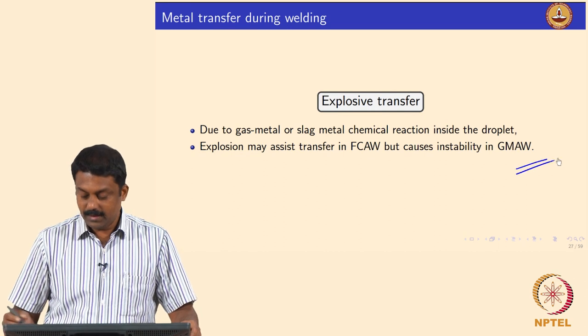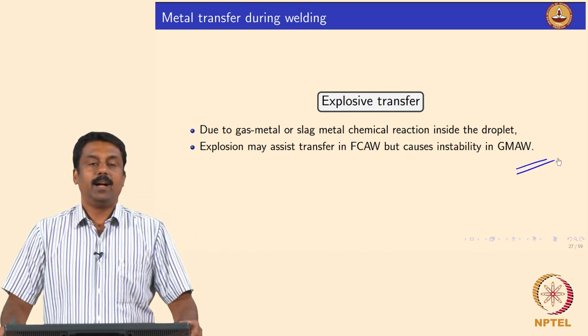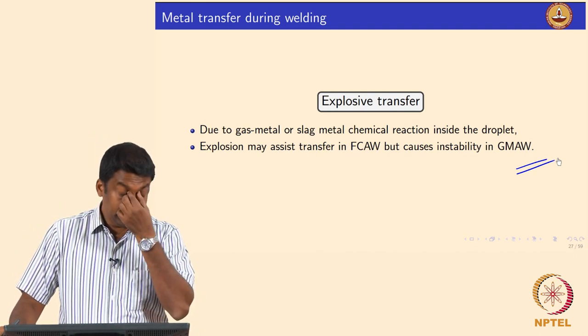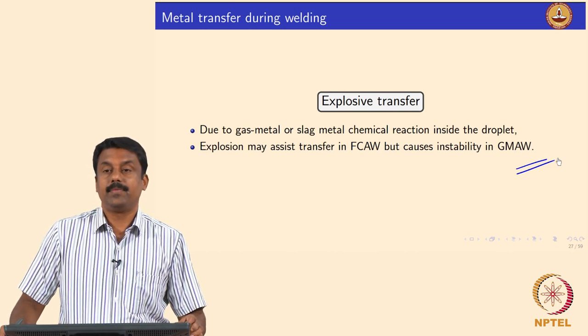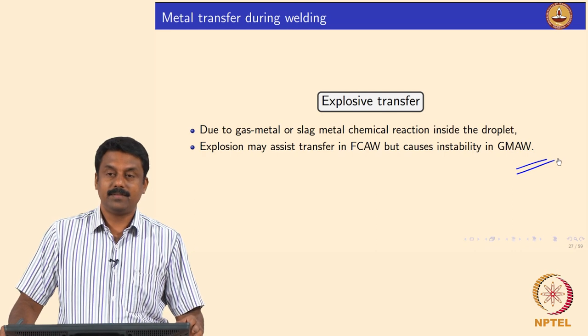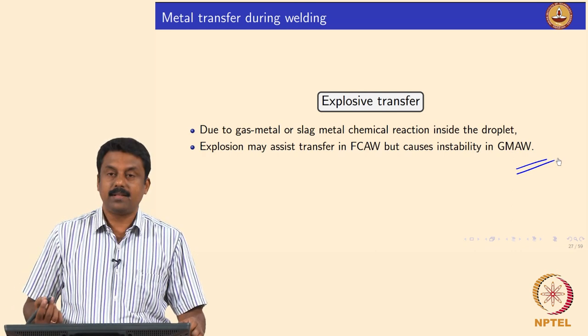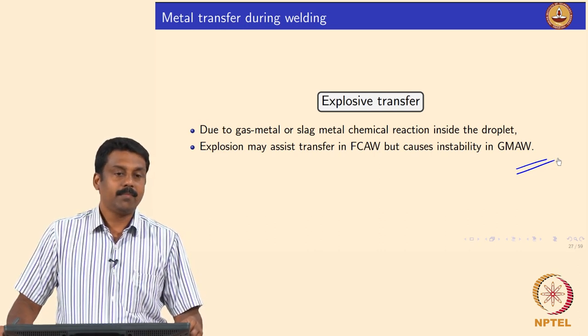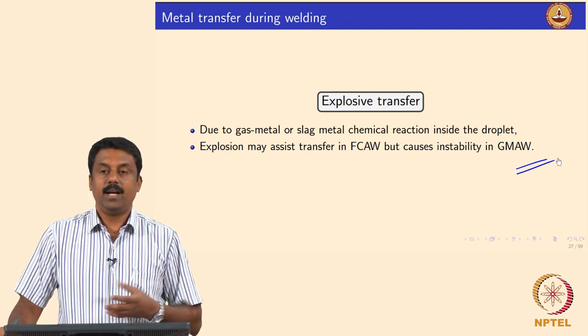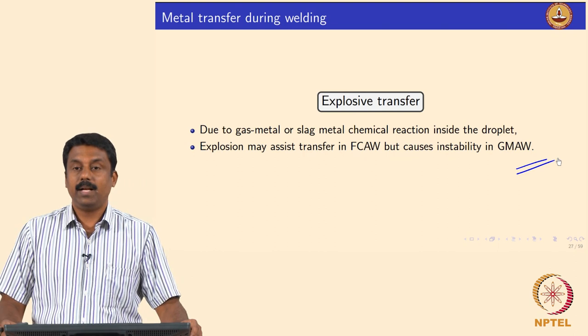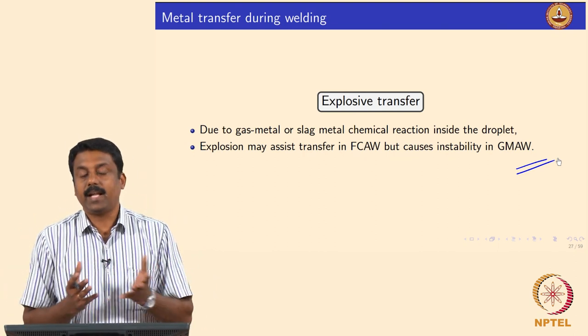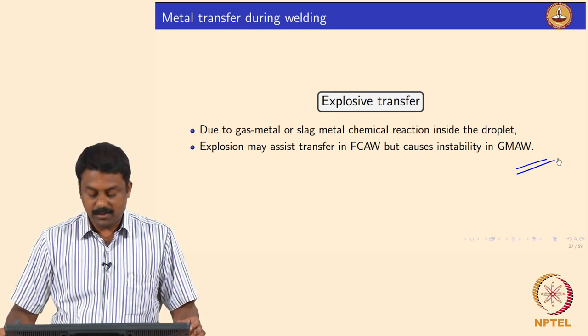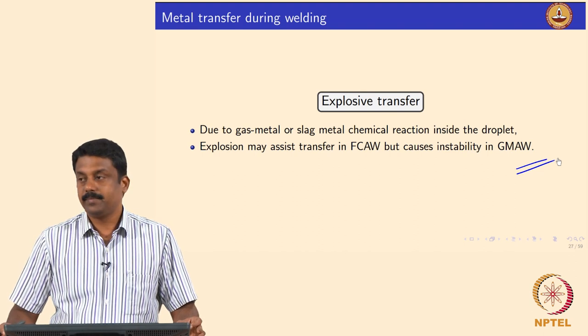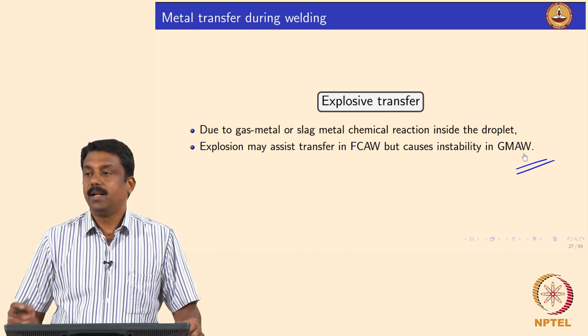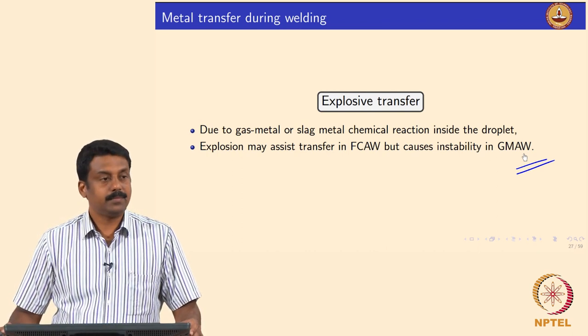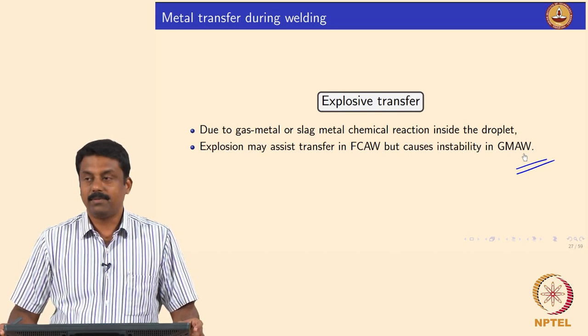In some cases, if you increase the current tremendously high and you also have shielding gas generated, especially in self-shielded electrodes, you may have an explosive transfer. Most of the cases it happens in self-shielded electrodes or flux core arc welding electrodes, where you have a very high current and a gas generated by the flux, and the gas pressure is contained. So you increase the plasma jet pressure and the Lorentz force, and you may expect an explosion of the droplet. It is an extremely unwanted mode of transfer in any case, because you can never weld by explosive transfer.